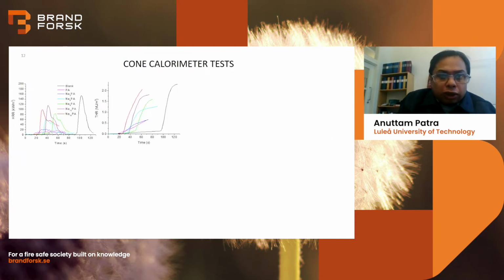Now I show the cone calorimeter test. This is where we stopped in the last project, our first project with Brandforsk. We used blank cloth, Na6Pa and Na12Pa, and the result was promising. For example, with Na6Pa, the total heat release, THR, was lower. So we wanted to explore it more.